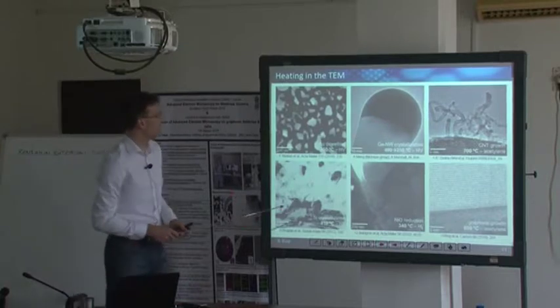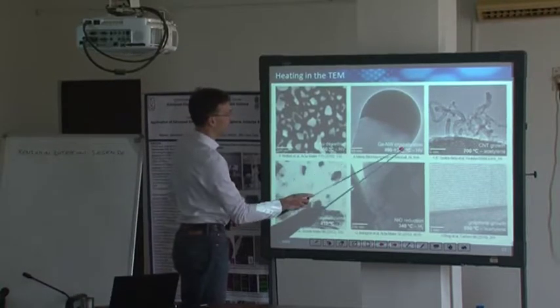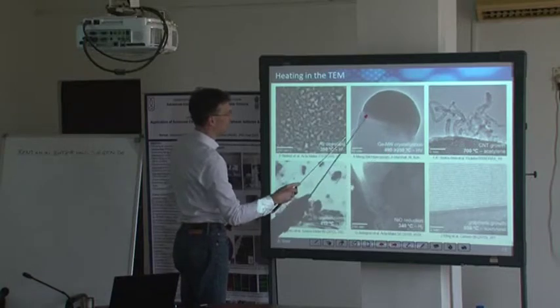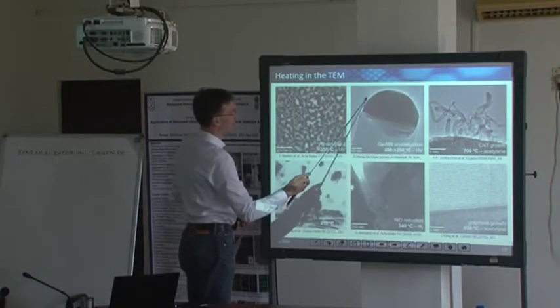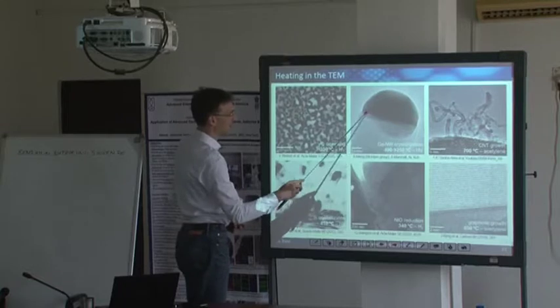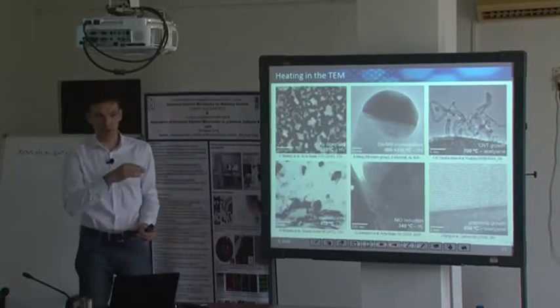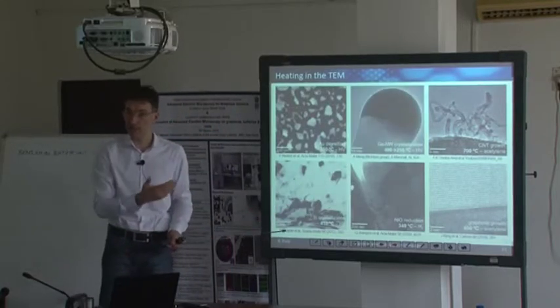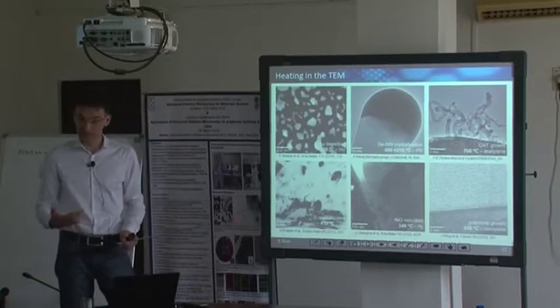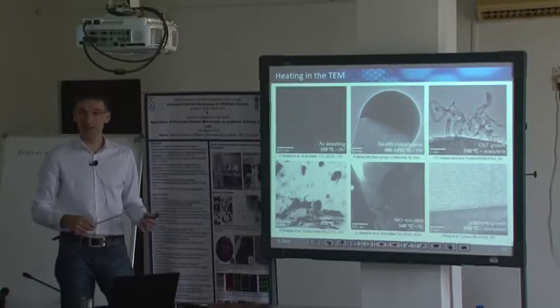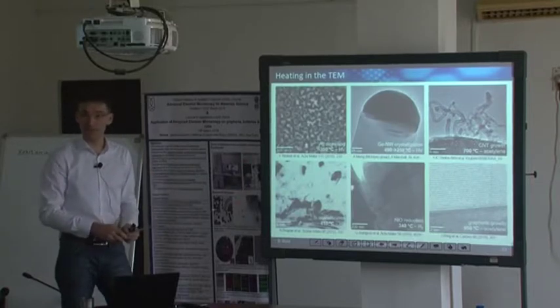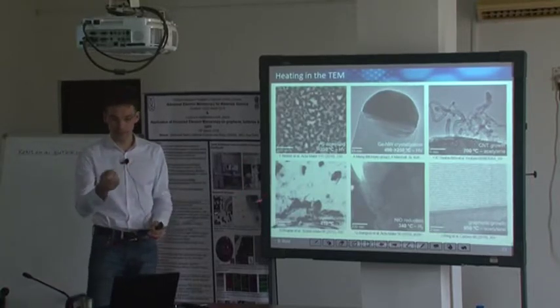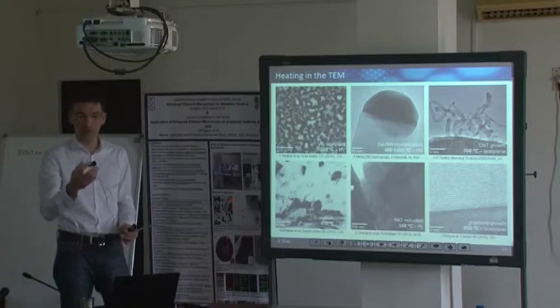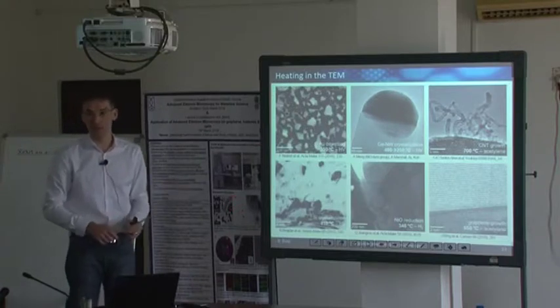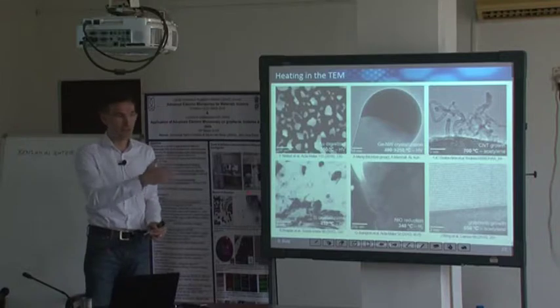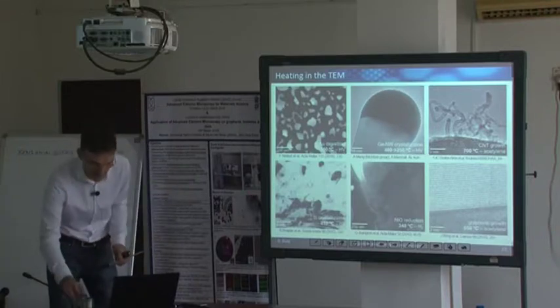This is the recrystallization here in high vacuum at different temperatures of this uppermost tip. So this is liquid here, now it crystallizes. And in principle, that occurs atomic layer by atomic layer if you look carefully. So structure formation is not that something just goes on in the bulk and it recrystallizes; it nucleates at some point, and then atomic layer by atomic layer, the material crystallizes. This is, for instance, a transformation of an amorphous phase to a crystalline phase.